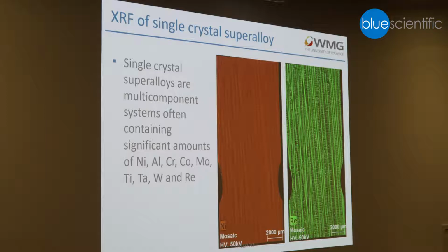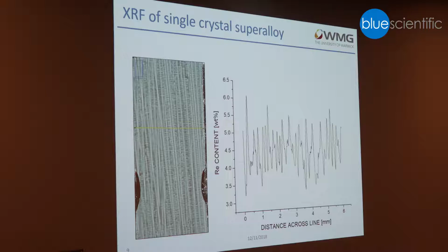So I can't tell you what alloy this is, but it's a typical single crystal superalloy. We can then, for example, on the rhenium, where we see the very clear dendritic structure, quantify the rhenium content across these dendritic arms.